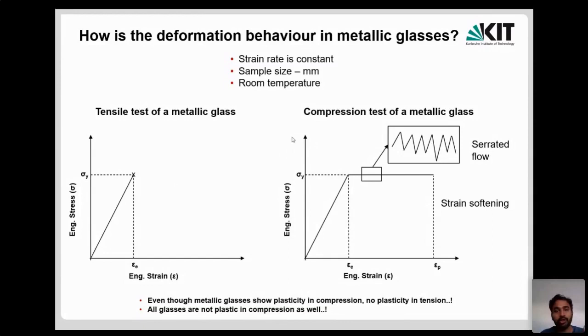Or there are some glasses which you can tune and you can get some plasticity out of it. In such glasses, you have a linear elastic regime and then you have a plastic regime, but the plastic regime does not show any strain hardening component like you see in the crystalline material. So it's absolutely flat. So this is quite interesting, because the glasses, why don't they show any strain hardening component? And if you look closely into the flat portion here, you'll actually see that there are these kind of load drops. There is a serrated behavior. And this behavior comes because of the shear band generation in the glasses, which is what I'm going to talk about later on. So there is a lot of change in deformation here. So the glasses behave differently compared to a normal crystalline solid. So that's the take-home message from the slide, that you have no plasticity in tension, but in compression, some glasses show plasticity. Okay.